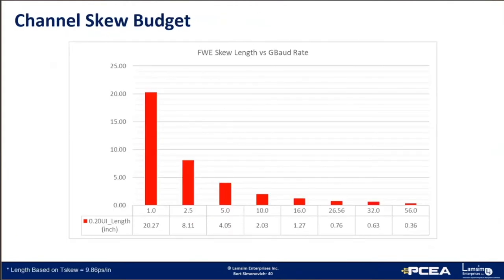So here's a graph plotting the fiber weave effect skew versus gigabaud rate. It's based on 9.86 picoseconds per inch of skew. And as you can see, the length of the fiber weave effect skew decreases exponentially with an exponential increase in baud rate. At 1 gigabaud, we can live with about 20 inches of skew. So it's unlikely to be an issue. But as we go past 10 gigabaud, we need to start paying attention.